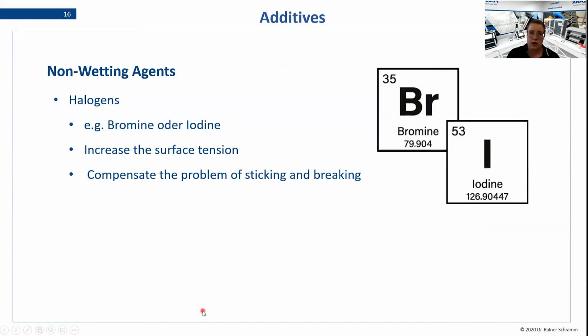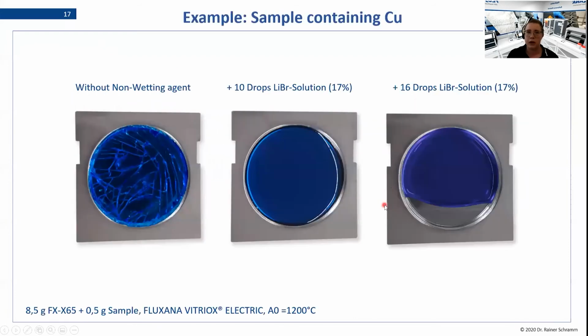What are non-wetting agents? Non-wetting agents are halogens. For example, bromine and iodine are used very frequently, and these increase the surface tension, so they will compensate the problem we just saw with the sticking and the breaking. What does that look like? We are having an example here of a melt that contains copper. That's why it's so nicely blue. And I first did a fusion without a non-wetting agent. And we can see that the bead is very flat and that it broke in a way that it cannot be used at all.